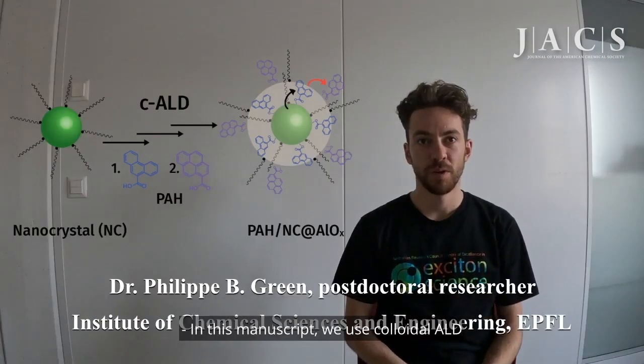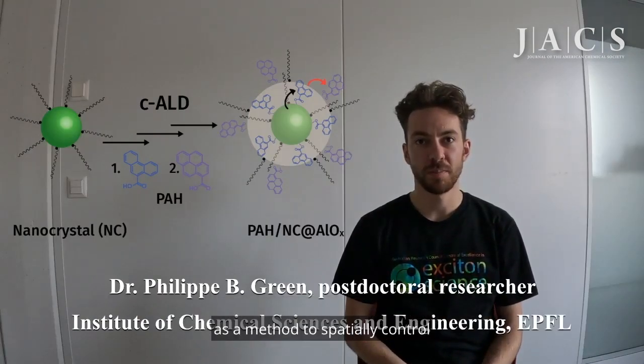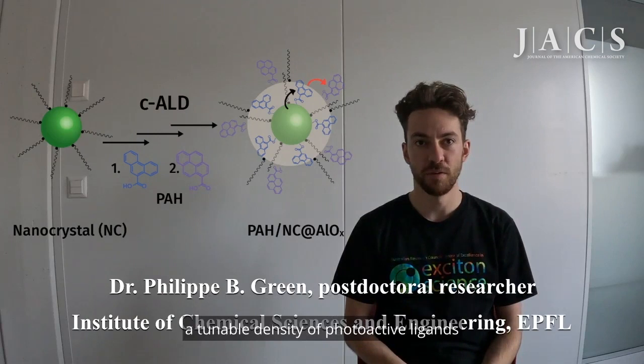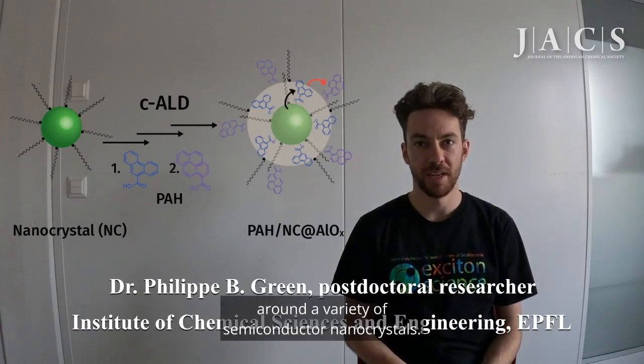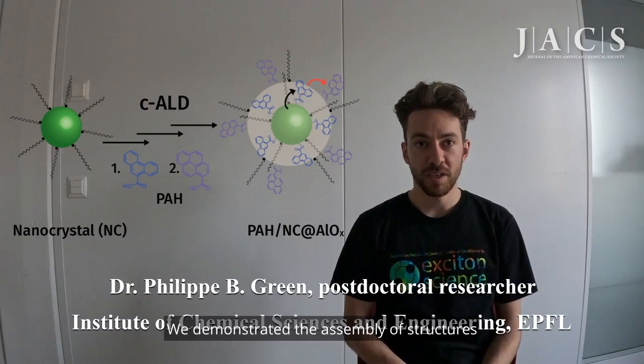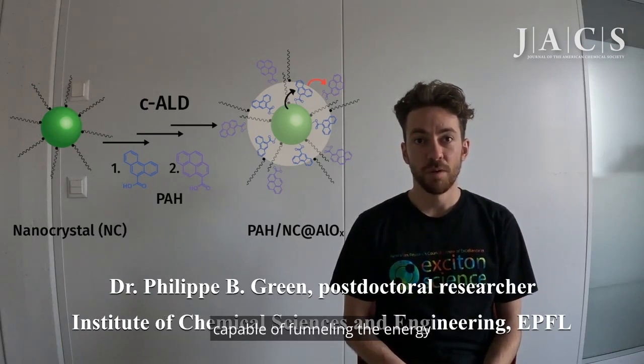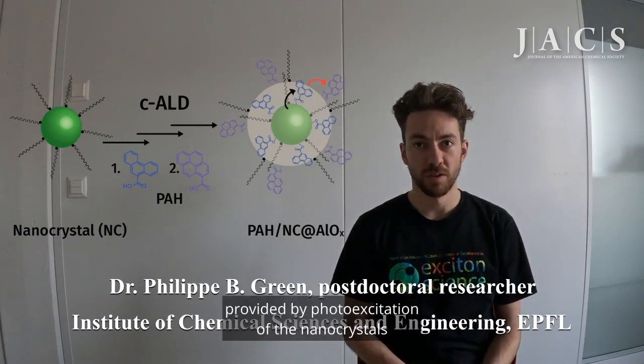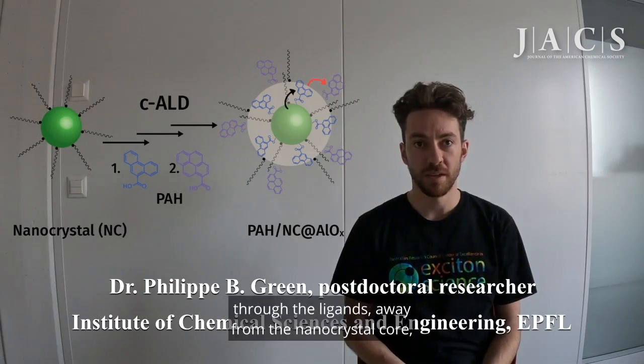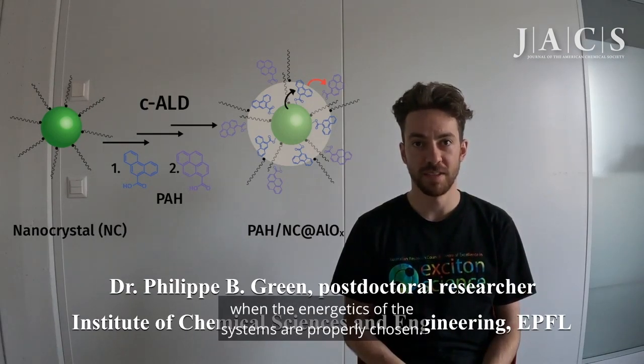In this manuscript, we used colloidal ALD as a method to spatially control a tunable density of photoactive ligands around a variety of semiconductor nanocrystals. We demonstrated the assembly of structures capable of funneling the energy provided by photoexcitation of the nanocrystals through the ligands away from the nanocrystal core, when the energetics of the systems are properly chosen.